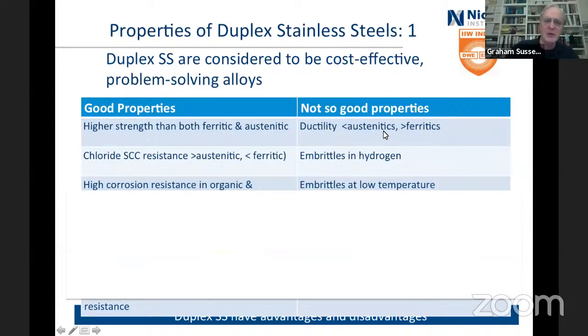Yeah, that's perhaps a problem, but usually not. Chloride stress corrosion cracking, very much better than the austenitics, less than the ferritics, which basically don't suffer from it. Unfortunately, because it's a duplex, it's got ferrite and austenite in it, and so it will embrittle with hydrogen. High corrosion resistance to organic and mild phosphoric acid, and it'll unfortunately embrittle at low temperatures. Actually, you can get some quite low temperatures, but you've got to be careful about it because it's the ferritic phase that actually embrittles.